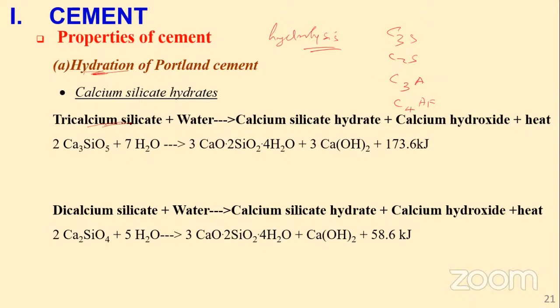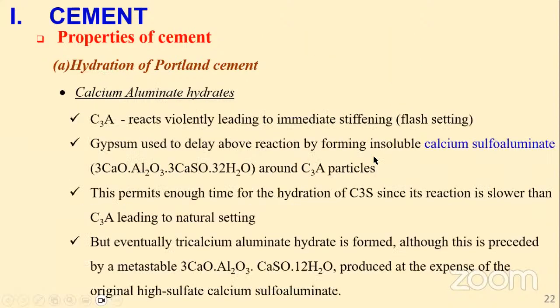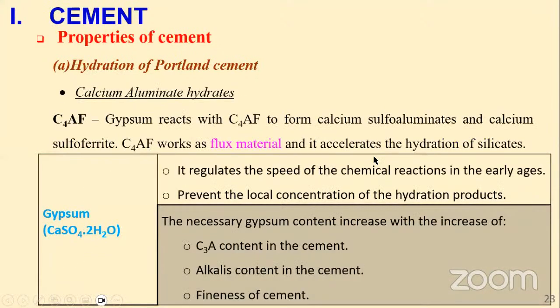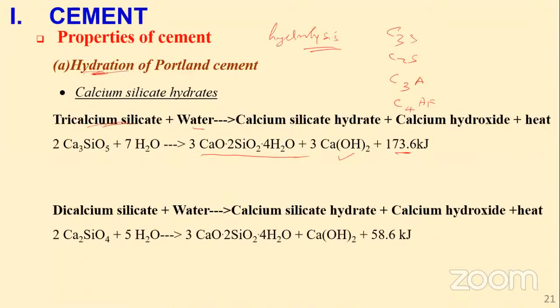So tricalcium silicate reacts with water to form calcium silicate hydrate. So they are becoming hydrated. Of course, they release calcium hydroxide, slaked lime, and heat. So you see, it's an exothermic reaction. So dicalcium silicate, when it comes into contact with water, again, it becomes hydrated. So hydration process, hydrolysis. So it becomes calcium silicate hydrate plus calcium hydroxide plus heat.